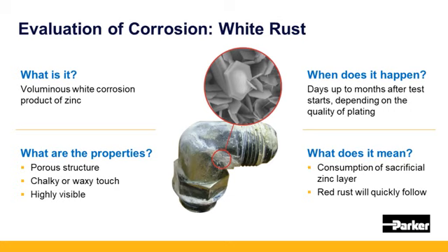Now let's look at the several types of corrosion products in more detail. First of all is the white rust. White rust is a white and voluminous corrosion product commonly found on zinc. The word voluminous means it has volume. And white rust typically is a mixture of zinc oxide and zinc hydroxide. When you touch it, it gives you a chalky or waxy touch and has a porous structure. That porous structure opens a passage for corrosion agents to further attack the metal substrate underneath the plating. And it's also highly visible.